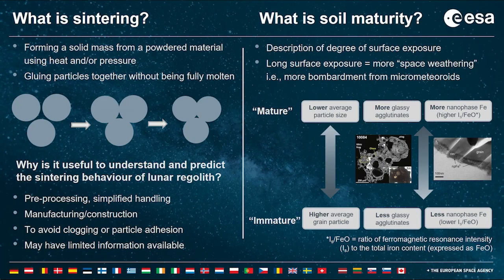So just quickly, what is soil maturity? Lunar soil maturity is just a description of the degree of surface exposure. So longer surface exposure means that it's had more space weathering. And in this context, the most important space weathering process is bombardment from micrometeoroids. So the mature material has a lower average particle size, more glassy agglutinates, and also more nanophase iron and these glassy rims that can be found on the surface of the particles. So that's represented by the term IS/FeO.